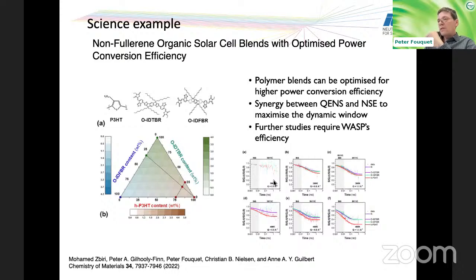And also that's a very rich point where you can, with techniques like neutron spin echo, look at the dynamics as a function of time. Whereas with time-of-flight spectroscopy, you can look at the dynamics as a function of energy exchange, which are properties that are related to each other via Fourier transform. So you can get a very global picture with these, combining these.